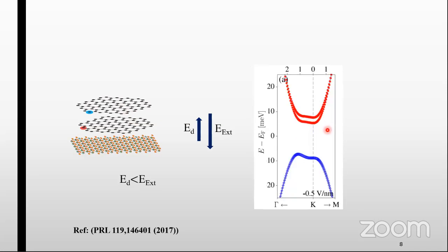If we are applying an electric field which is much larger than the intrinsic electric field, then in that case, the valence band will be formed from the non-dimer atomic orbital of the top layer, and the conduction band will form from the non-dimer atomic orbital of the bottom layer. Since the bottom layer is always in direct contact with WSe2, this time the conduction band will show the splitting since it is forming from the atomic orbital of the bottom layer.